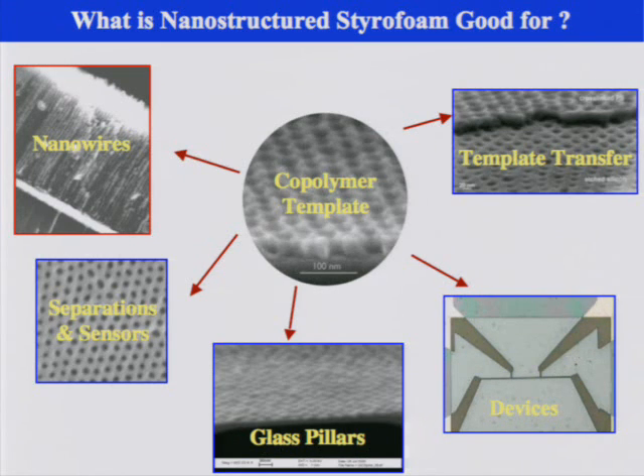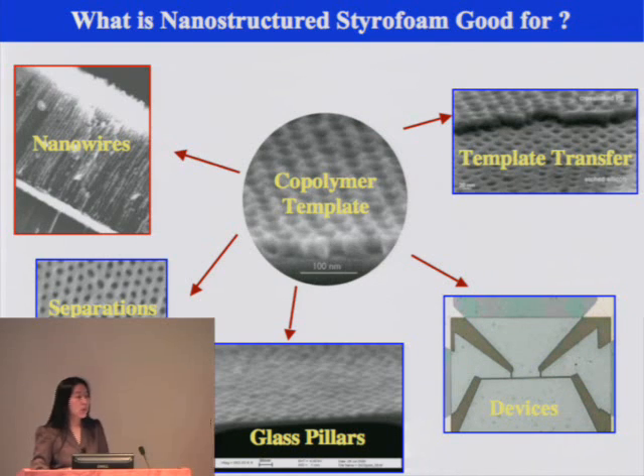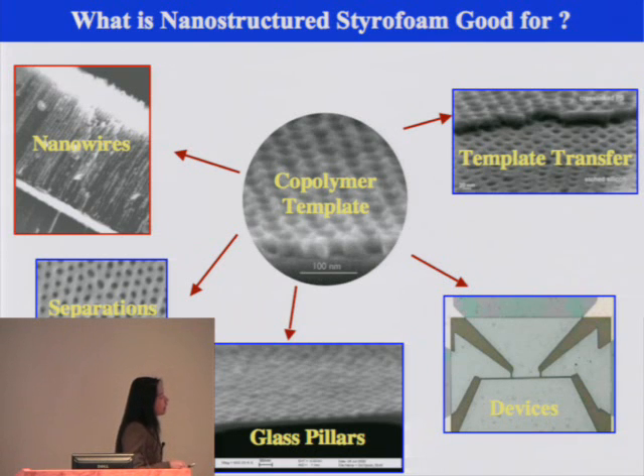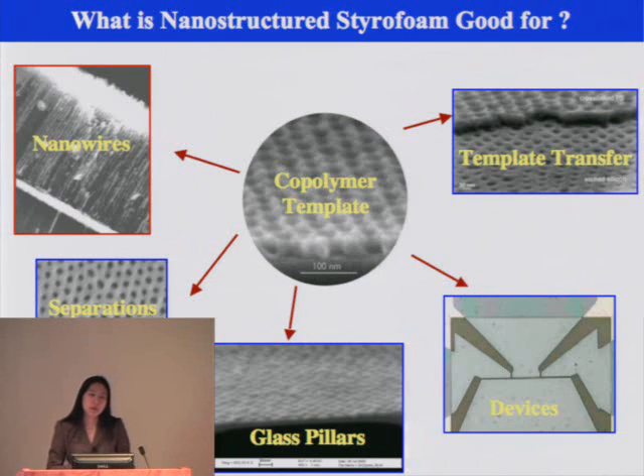Alternatively, you can deposit a cobalt nanowire in there, and as you start to control the aspect ratio of the cobalt nanowire, you can actually use each individual one as a storage unit. You can imagine that with this nanostructured styrofoam, it's going to be hard for me to use this for memory storage because I need to have a reader and a writer, a read and write head on it.